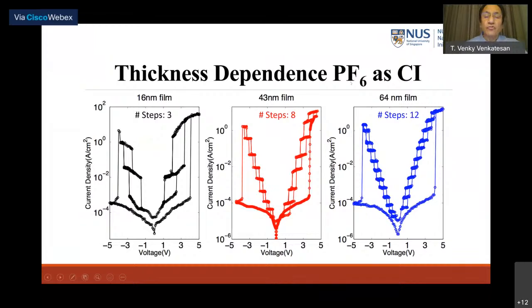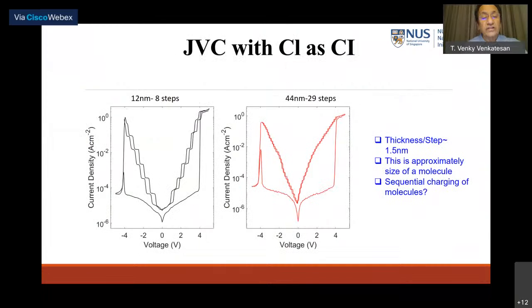What happens with a smaller counter ion, like chlorine, for example? Can we then switch only 1 layer? And the answer is yes. For example, a 12 nanometer film shows 8 steps, indicating that we're switching only 1 layer at a time. A 44 nanometer film shows 29 steps. This is exactly what we expect for a 1.5 nanometer diameter for the molecule.